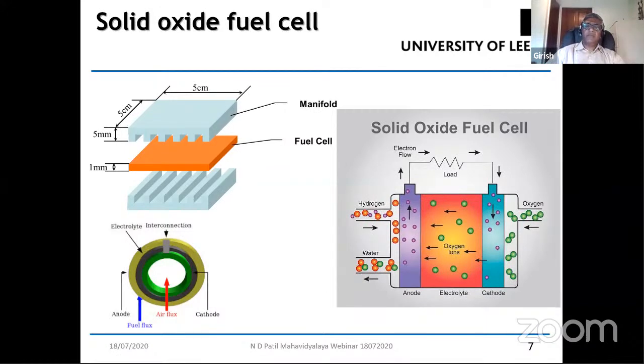Now, one of the problems in achieving the theoretical voltage is that you don't get the theoretical voltage from the fuel cell, mainly because there are places where the voltage drop occurs. One of them is at this interface, which is the anode and the electrolyte interface. Then the cathode and the electrolyte interface. And the electrolyte itself has its own resistivity. So high surface area anodes and cathodes have been used in order to provide greater triple phase boundary to facilitate the electron exchange that is taking place at the two different interfaces at the cathode and the anode.